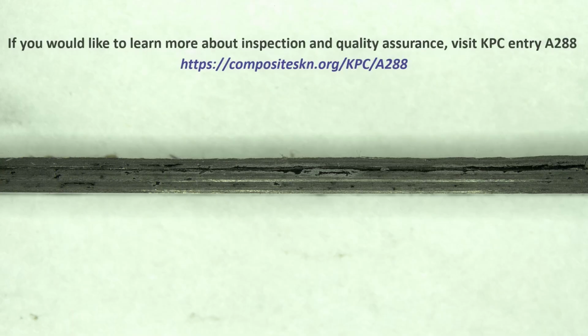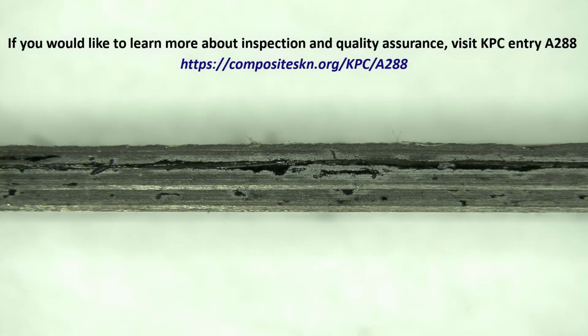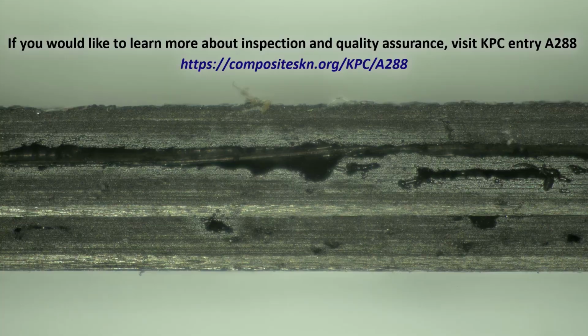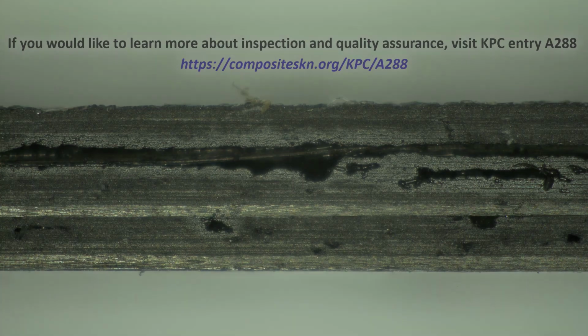After removing the cured part from the tool, we can see that the fibers have not been well saturated by the resin. The lack of consolidation pressure has prevented the part from becoming fully consolidated. In a cross-sectional view, voids are visible within the laminate. If the part had been under full vacuum, entrapped air would have likely been removed from the laminate.